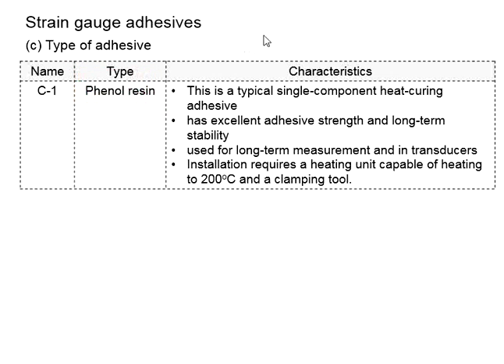Next, we have phenol resin. It is labeled as C1. It is a typical single component heat curing adhesive that has excellent adhesive strength and long-term stability. It is used for long-term measurements and in transducers. The meaning of long-term measurement is that you intend to monitor the conditions of your test specimen over time. Normally, the strain gauge will remain there. Over a period of time, you measure the strain gauge again, over and over again. Now you require the adhesive to be strong enough and last over a long period of time. Now the installation requires a heating unit capable of heating to 200 degrees Celsius and a clamping tool.